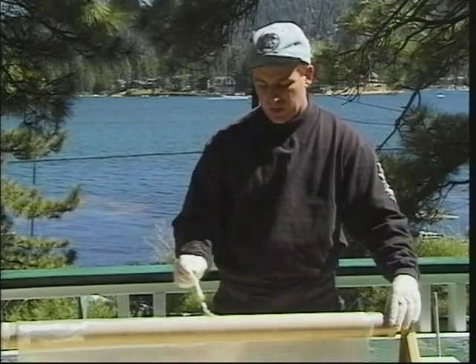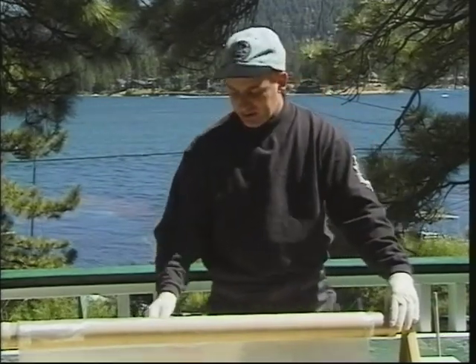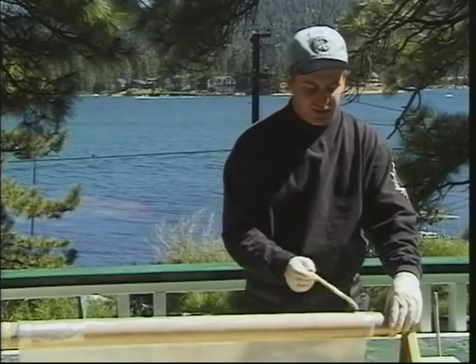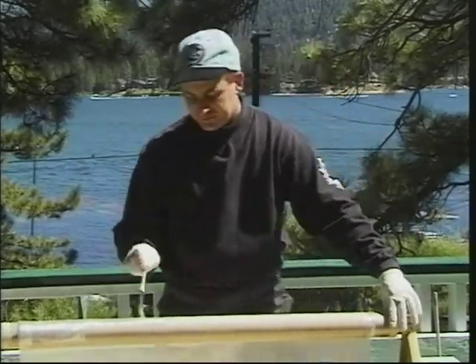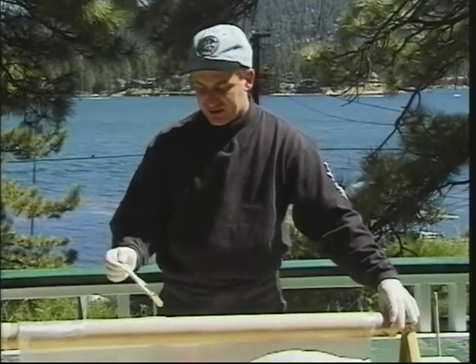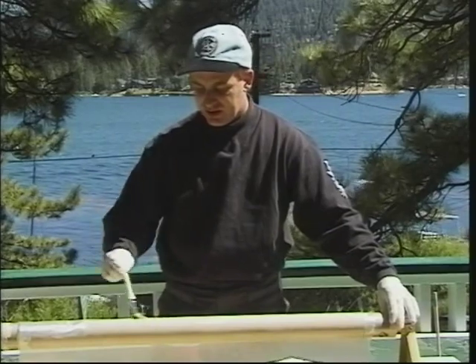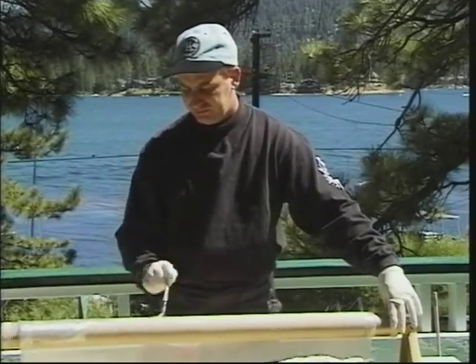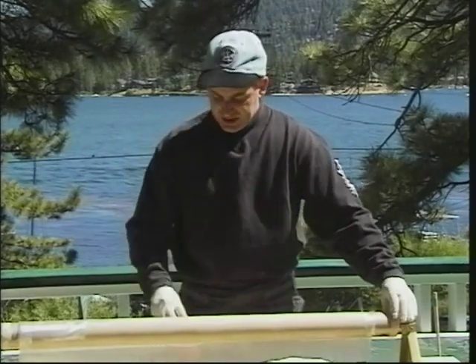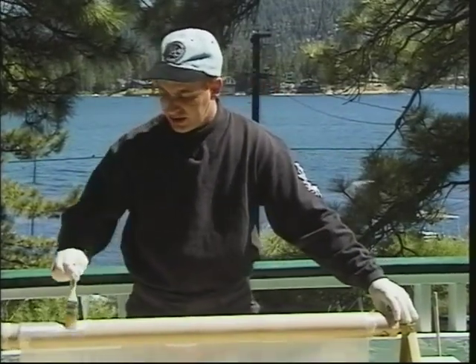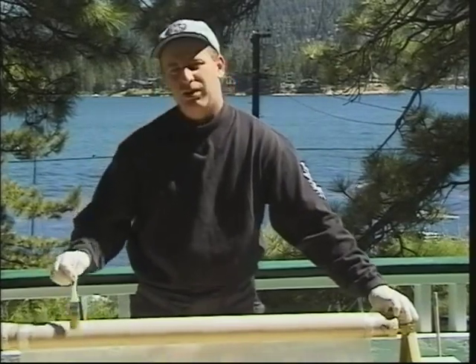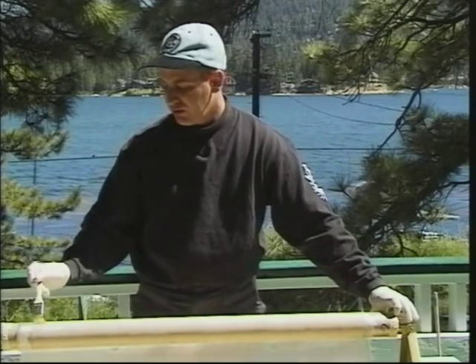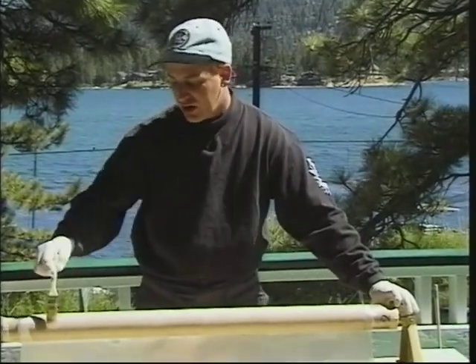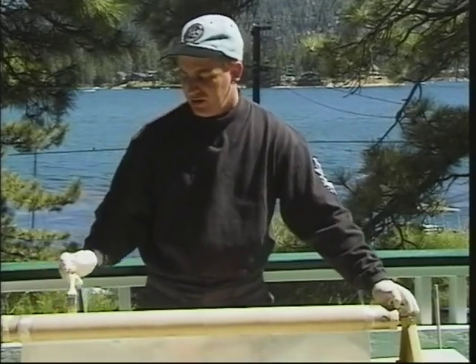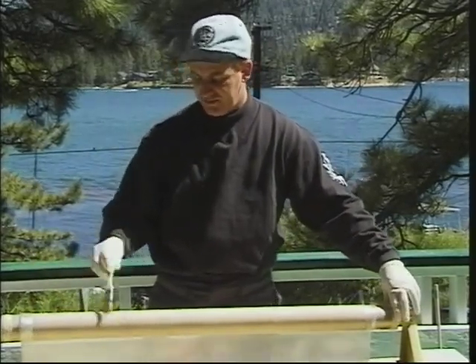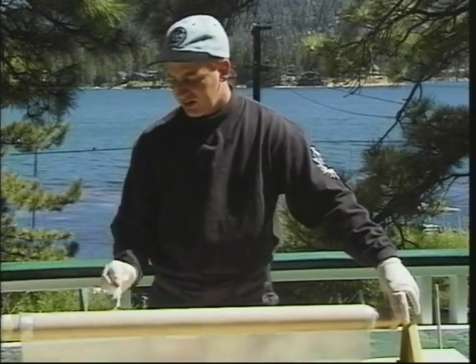Figure on wrapping your tube twice, and then look at the material specifications in the vendor catalog as far as tensile strength and all of those things to see what material fits the amount of strength that you want to get onto your airframe. Now in this tube, we're also just wrapping this glass cloth as a reinforcement onto the base paper tube. You can do this also with phenolic tubes. You can use just one wrap of glass on a phenolic tube. If you use the 5 to 8 ounce glass range, that will provide you with a very strong structure.